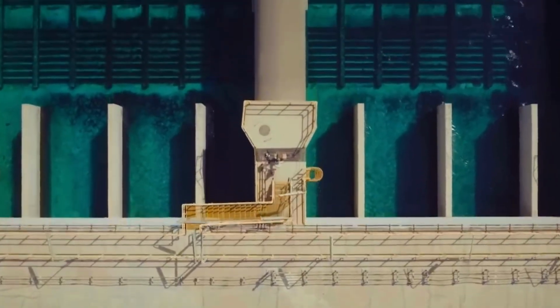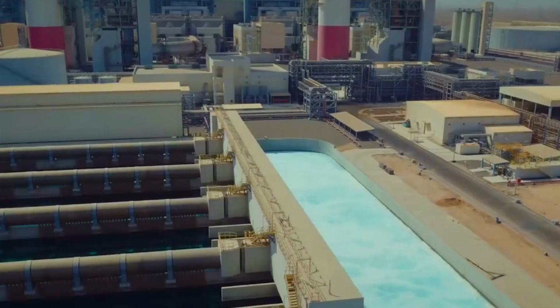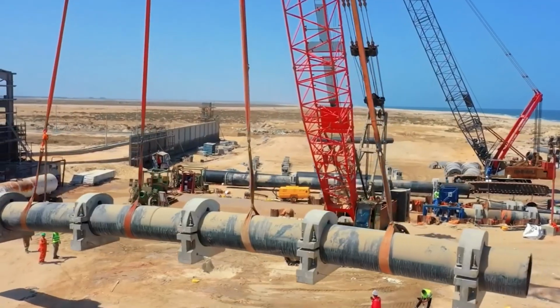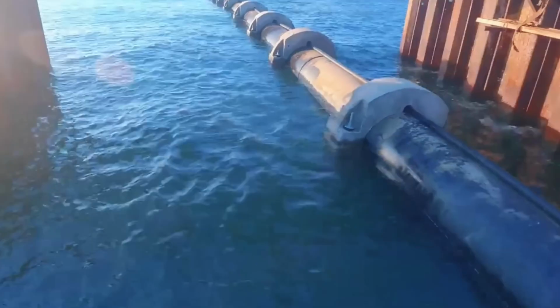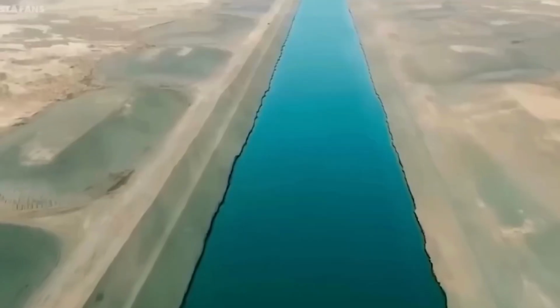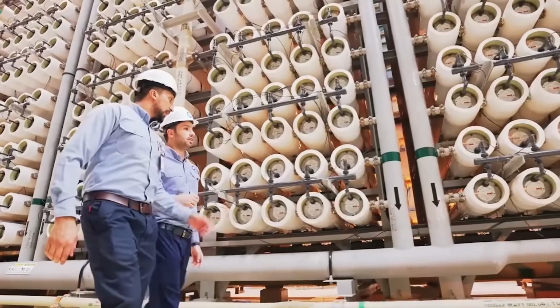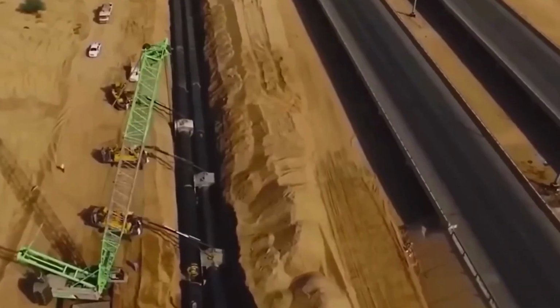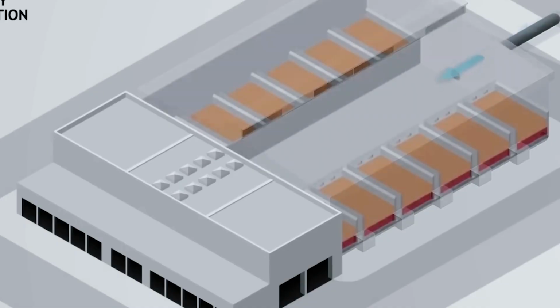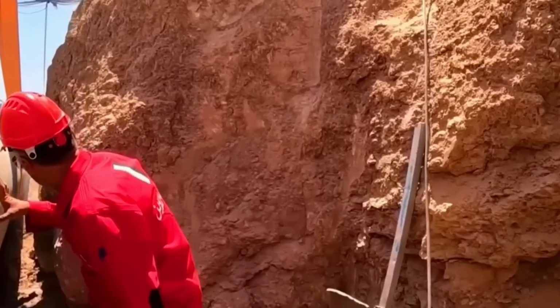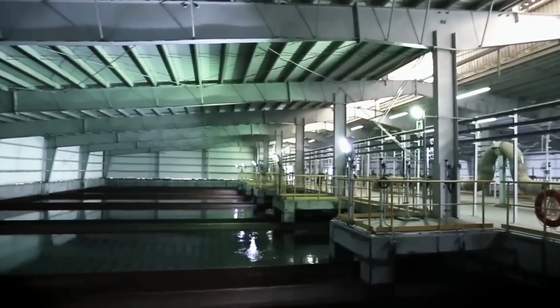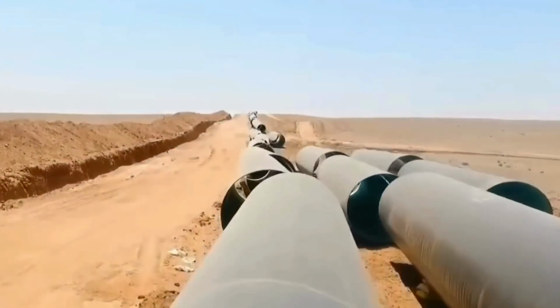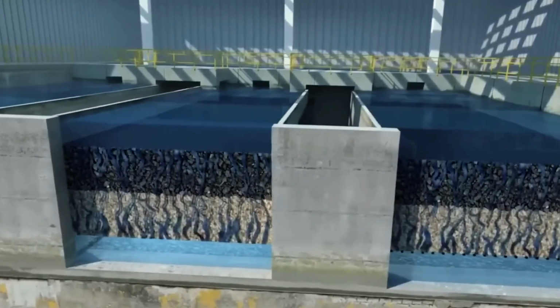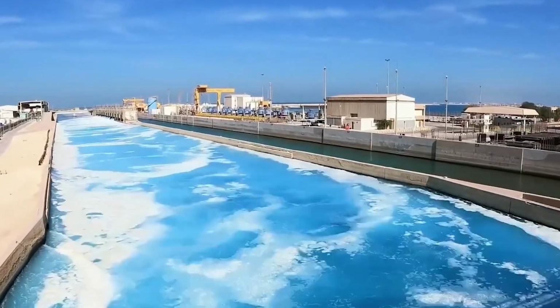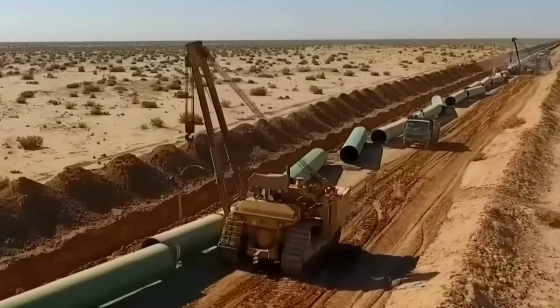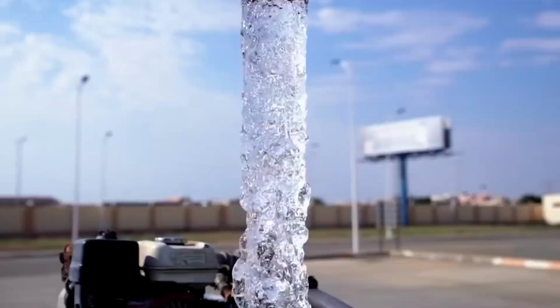A multi-axis rolling machine bends the plate gradually until the edges meet and the tube takes shape. Next comes welding, a long longitudinal seam that turns a rolled shell into a pressure-holding pipe. After welding, the seam is cooled, inspected, and ground smooth to remove sharp edges and burrs. Both ends are beveled, so future field joints can fuse cleanly and seal tightly. Sections are typically more than 10 meters long, enough to reduce the number of welds, but short enough to transport across long distances. Quality control is relentless.